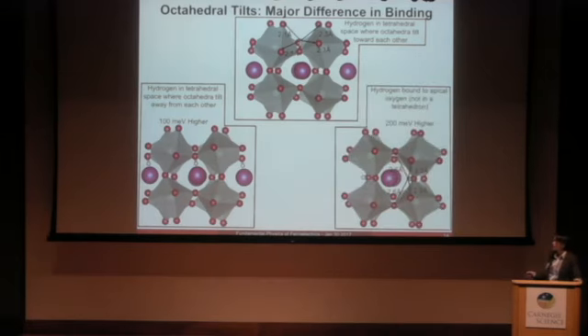Also, if we look at the inequivalent oxygen site along the c-axis, because there's an in-phase rotation along this axis, you don't end up with a tetrahedra. So you get a different space where the hydrogen is coordinated, and this becomes even higher in energy. So going forward, this is going to be the type of structure we focus on. So keeping this hydrogen in this area where the octahedra are canted toward each other.